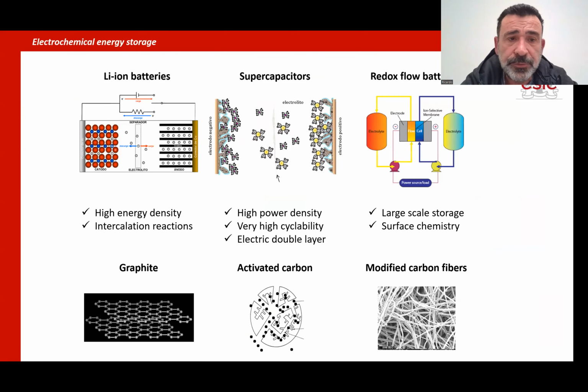But here, just to finalize, you have the scheme of why different electrochemical systems have different carbon materials as electrodes. In lithium-ion batteries, as we have seen, we use graphite because of its structure, and we are working with intercalation of lithium inside the structure of the graphite. In supercapacitors, we use activated carbons because of the high surface area, and that gives us high power and very high cyclability. And the redox flow battery is a very good system for large-scale storage. We can easily move to megawatt-hours of energy stored.